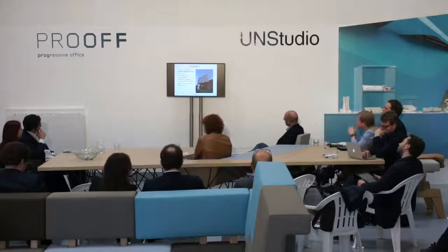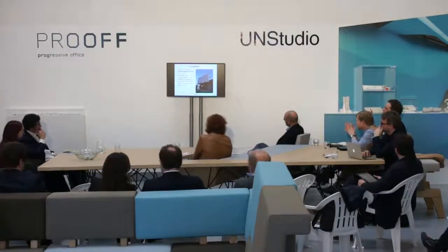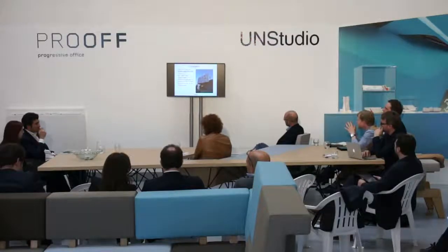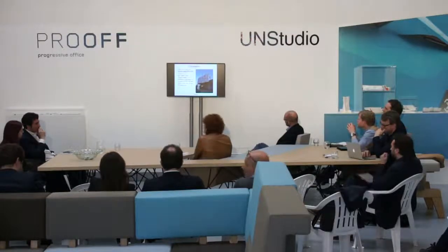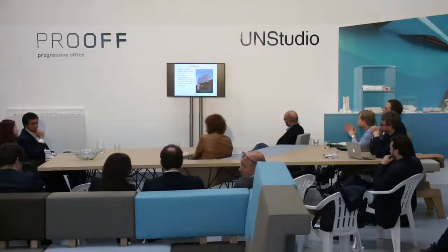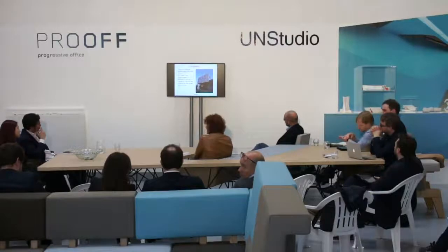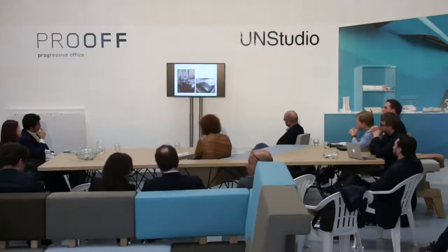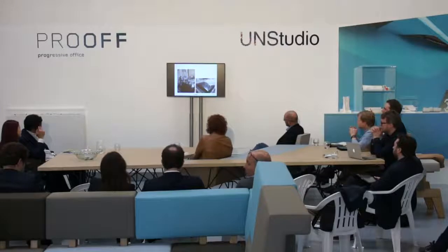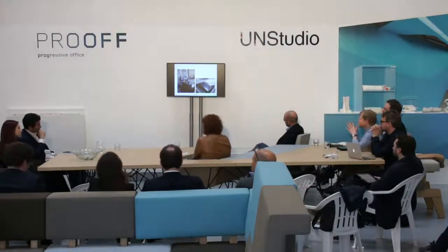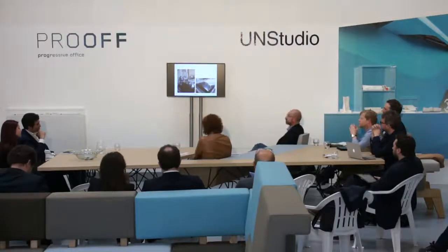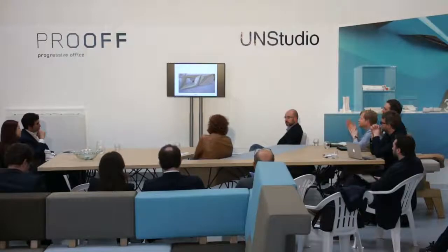Again, the installation is extremely fast. We calculated basically to pre-assemble 2 to 3 panels on the ground within 2 hours, and then the pre-assembled segment again is fixed to the building in another 2 hours, very fast. I show a few images of the mold. We did a few samples because also the surface finish was quite tricky. Actually, UNStudio gave us quite some tasks there, which was nice.